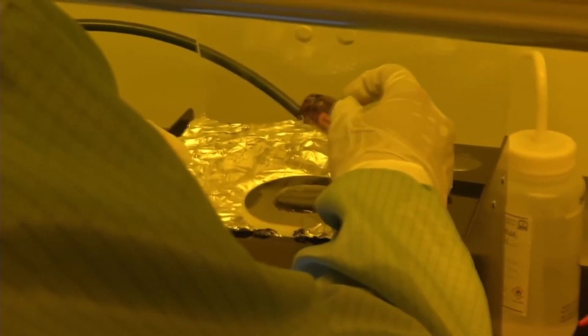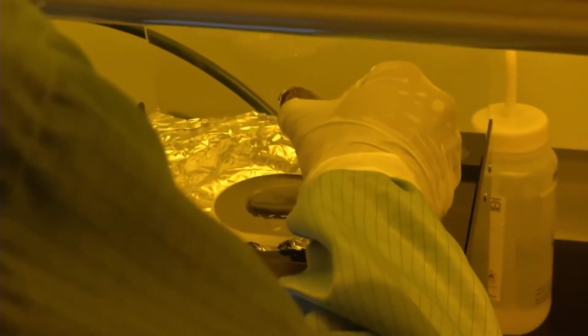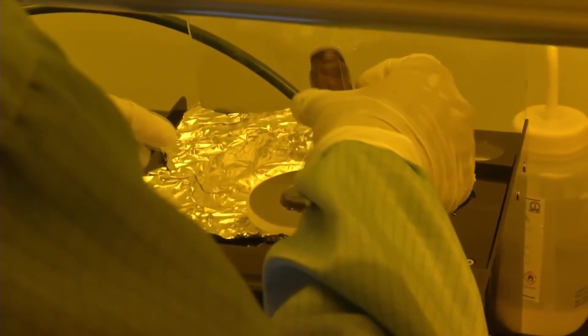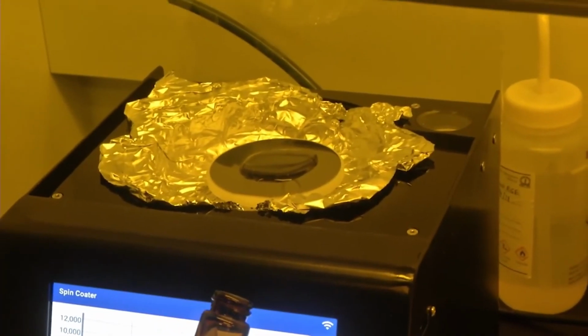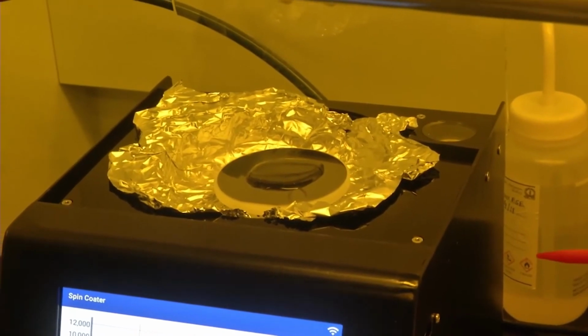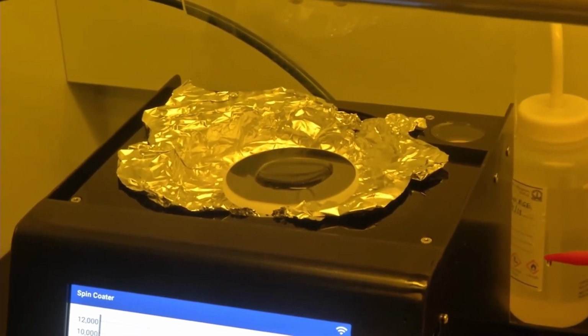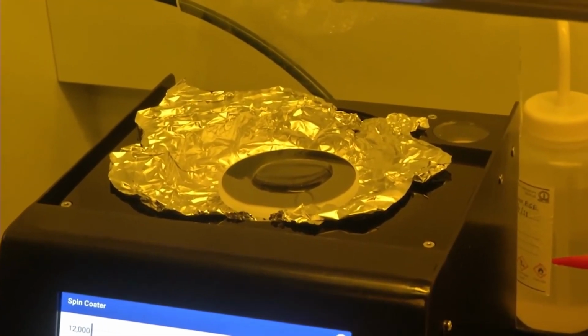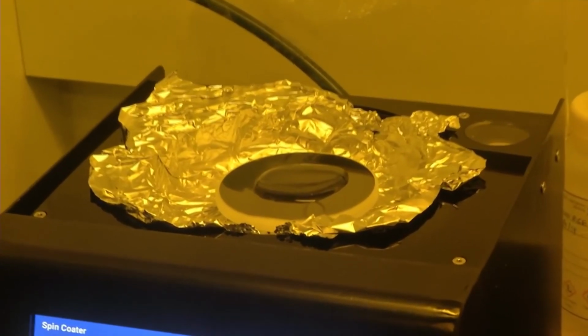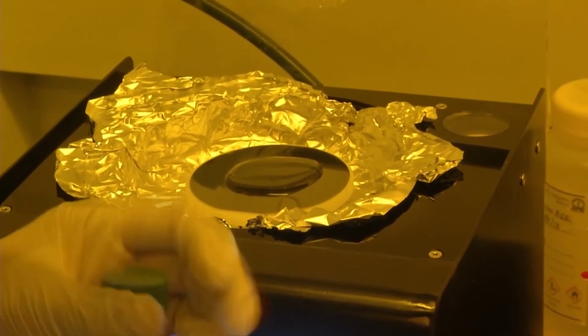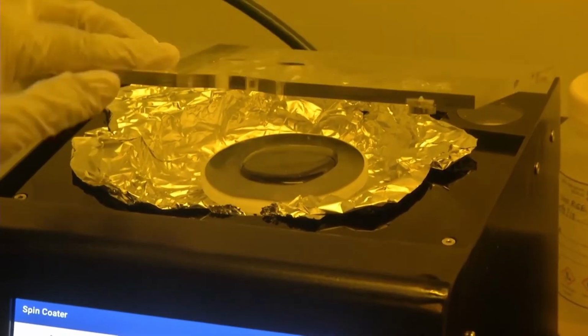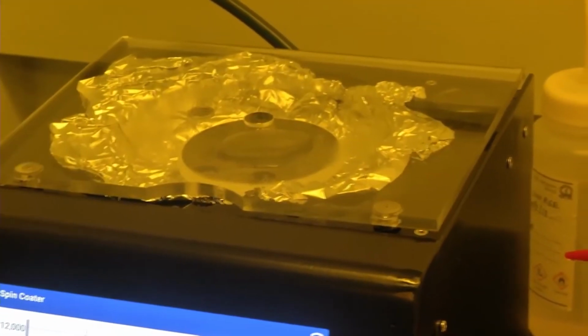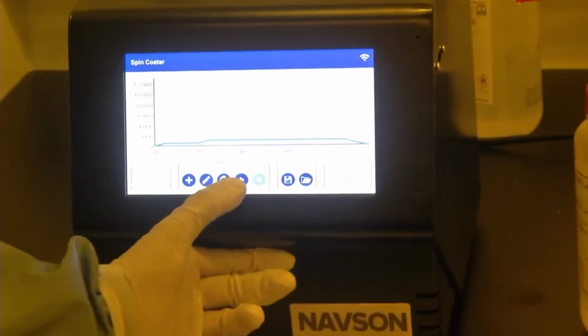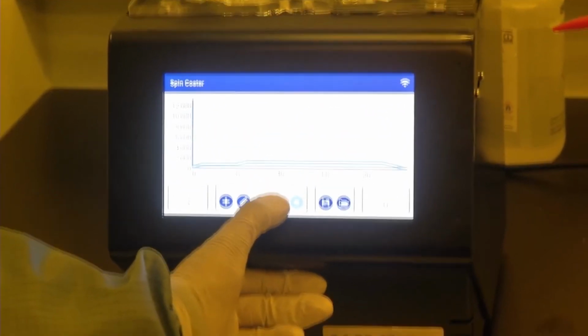As we can see, he is gradually pouring the polymer precursor on the silicon wafer, and now since it is gradually poured, he will wipe off the excess polymer from the vial to keep it clean, so that there is no contamination next time when we spin coat. And now he will close the lid and press the play button. As we see in a general music player, in a similar way we will press the play button, which means we can start the spin coating process.